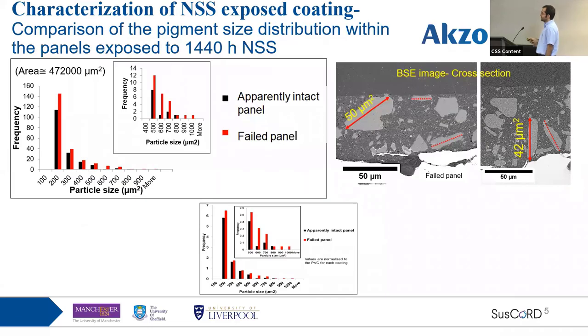The other thing that this analysis showed me is that we can use those data to look at the size distributions of the pigments. Of course, we had higher pigment volume concentration within the failed panel, which probably results in a higher number of pigments within these coatings. And I'm looking at the larger pigments in this graph. In order to compare them, I needed to normalize them. What I have done is to normalize these numbers with the PVCs. And even after we normalize them, when we divide these numbers by the PVC that we calculated here, we still get higher pigment numbers for the samples that failed.